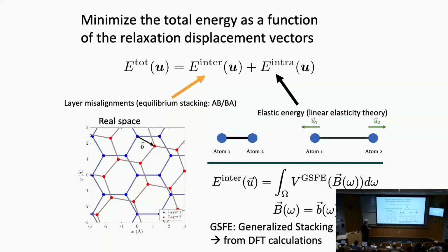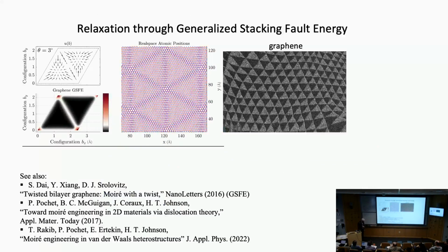And the interlayer term is an integral over an energy landscape for all the relative displacements of the two layers, which generate all these local environments that I mentioned, and includes a functional U of the rigid displacements. So minimizing with respect to this functional gives us the lowest energy. And with this, we can produce these kinds of pictures.